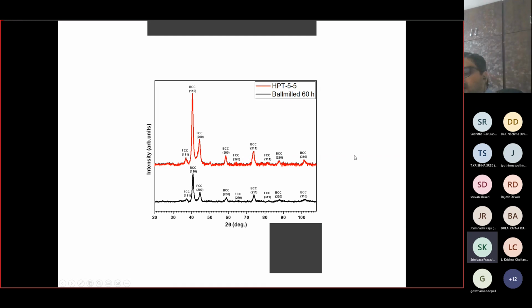And then there is a different technique called high pressure torsion. Normally, high pressure torsion means you apply very high loads at very high strain rates so that the microstructure gets refined. This is one way of making a nanostructured material from coarse grained materials. But in this case, we did not use it for structural refinement. Instead, we use this technique to compact the powders into bulk components so that you can measure the mechanical properties. At the same time, the whole process operates only at room temperature. You will not see any grain growth. So even after high pressure torsion, the structure that we have seen after ball milling has remained intact.